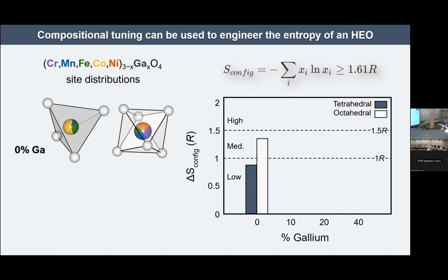And whether that actually matters is, I would say, significantly up for debate. And you could also debate whether it's valid to add these 2 configurational entropies together to come up with a combined sublattice entropy. Nonetheless, this is the true sort of configurational entropy of this material.